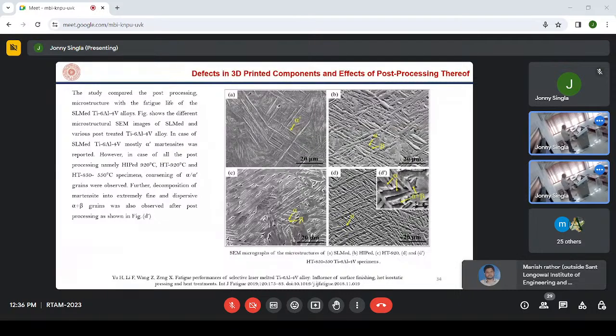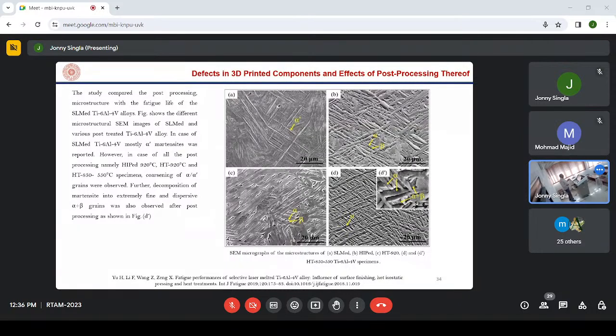Now when you supplement your testing results with characterization, with SEM study, you can see why there is improvement in the fatigue strength. So this is the reason for the improvement in the fatigue strength. Now if you see, this is your martensitic structure, needle-like structure. As-built AM components have this SEM surface morphology. Microstructure will be like this. Now these needle-like structures have high strength, but they reduce ductility. This is called martensitic structure, alpha prime. When you carry out post-processing heat treatment or HIP, then the structure will change like this.